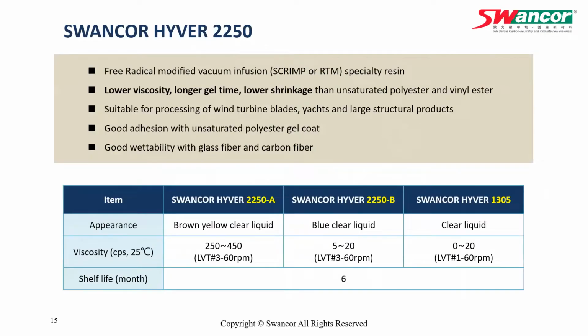And from this slide, we'll show you some technical issues for SWANCOR HYVER 2250. First is a radical modified vacuum infusion resin with lower viscosity, long gel time, and lower shrinkage compared to UPR and VR. And it's suited for any kind of large structural product with infusion process. And it has good adhesion with the UPR gel coat and good wetting ability with glass and carbon fiber.